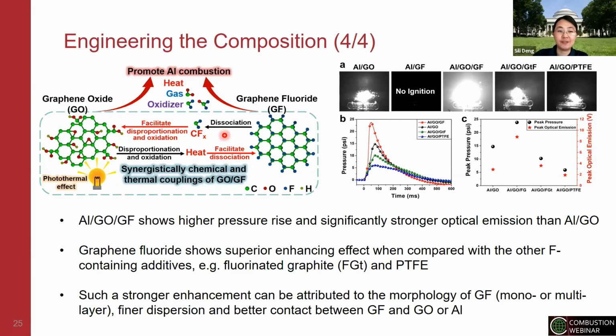So there is a synergistic effect going on here, meaning that the graphene oxide, upon the flash ignition, will release heat that facilitates the dissociation of the GF. And after the dissociation, it will generate some radicals that further enhance the disproportionation and combustion of GO. And they altogether provide the ignition energy for aluminum and some radicals to further oxidize the aluminum and remove the oxide layers of the product such that the reaction can continuously go on. So the take-home message is, yes, with the addition of GO and GF, we can see a very clear trend that we have an increased pressure rise as well as strong emissions due to the combustion of aluminum.